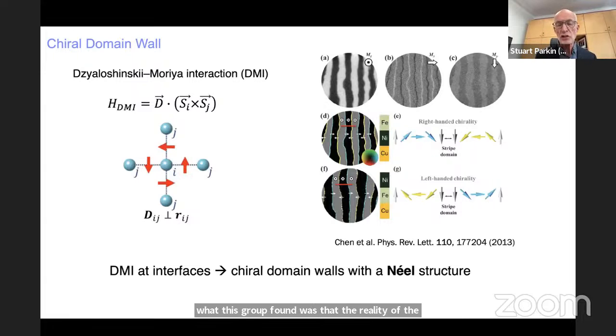This is a beautiful demonstration that interfaces in particular can give rise to a new form of an exchange interaction that is of a vector type. And this means that it directs the magnetization so that the magnetizations of neighboring moments want to be orthogonal to one another through this so-called Dzyaloshinskii-Moriya exchange interaction, which is shown on the top left. And this leads to, in the simplest system, as shown here, in this cubic system, this Dzyaloshinskii-Moriya interaction will be the same, let's say, in all directions.